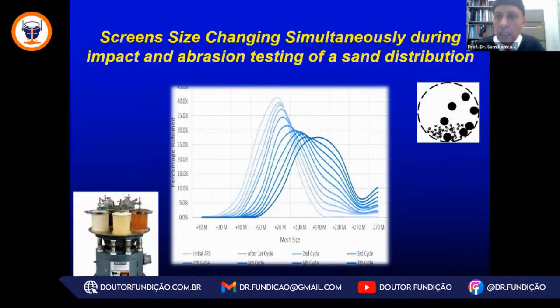And that's because of the compounds that we form in the casting process. Some of these changes for these sands are not only due to high temperature exposure during casting, but also after we've used these chemically bonded sands. I have mentioned they are more expensive granular media compared to silica sand, so we must recycle them. And in the reclamation process, they see more of this impact and abrasion due to thermomechanical reclamation.